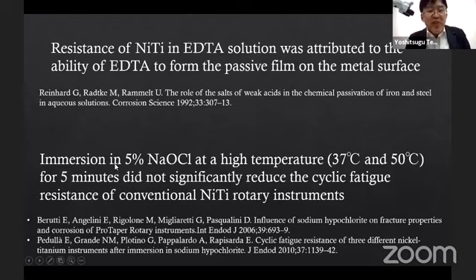Immersion in 5% sodium hypochlorite at a higher temperature, 37 degrees or maybe 50 degrees, for 5 minutes did not significantly reduce the cyclic fatigue resistance of conventional nickel titanium instrument. So if you use an instrument only 5 minutes in the presence of sodium hypochlorite, you are still okay. You don't lose any cyclic fatigue resistance. But it's better to use EDTA to increase the resistance to fracture.